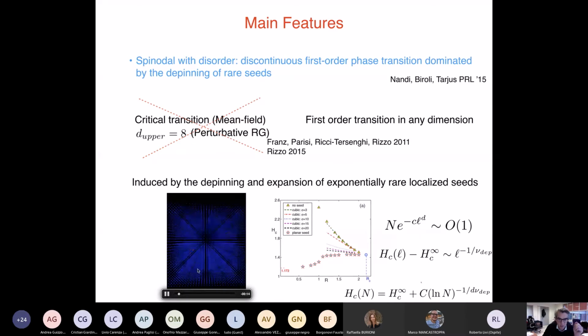And so what you have seen, and I do it again, is that it starts from somewhere, a small droplet here, and then this droplet just becomes larger and larger. What we understood is that what is driving this discontinuous jump is the existence of very rare seeds or droplets of the other phase, which, since it is a random system, you have a certain probability to have somewhere in the system if the system is large enough. And then this droplet can expand and invade all the system. Now, one can show that the bigger the droplet, the easier it is for it to expand.